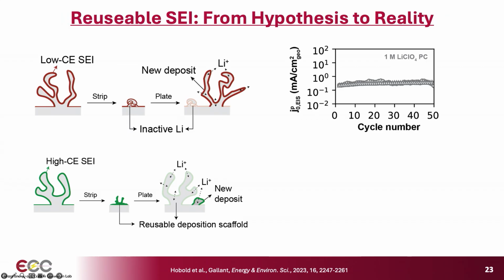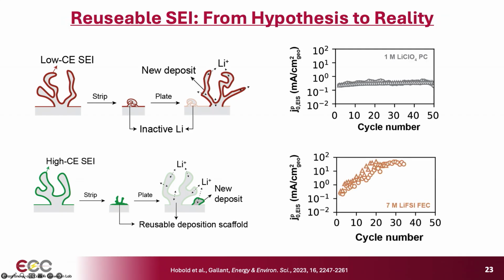In contrast, when you have a high Coulombic efficiency SEI, we propose that you plate it, and then you can strip it. But because this material now has a very facile ability to exchange lithium, you can actually plate lithium underneath it. And so what that would lead to is the ability to kind of reuse a scaffold. And then you would have relatively lower new surface formation, hence high Coulombic efficiency. And that would correspond with high J naught.